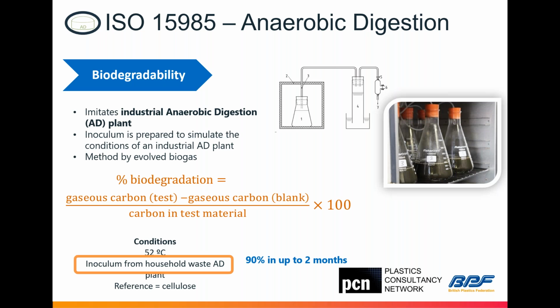Okay, then we move to anaerobic digestion. The anaerobic is a closed system where you take all the air out, you take some material from the anaerobic digestion, mix it with your plastic, and then monitor the increase of CO2 and methane in the system. Not only do you have CO2, but you have methane as well in the anaerobic digestion system. Usually the test temperature is 52 degrees, but as I said, that depends on which anaerobic digestion plant you want to send your material to. The times are much shorter, like 2 months compared with industrial composting. All you need to do is monitor the methane and the CO2. And then you need a conversion of the organic carbon to methane and CO2 of 90% in order to be classed as biodegradable.